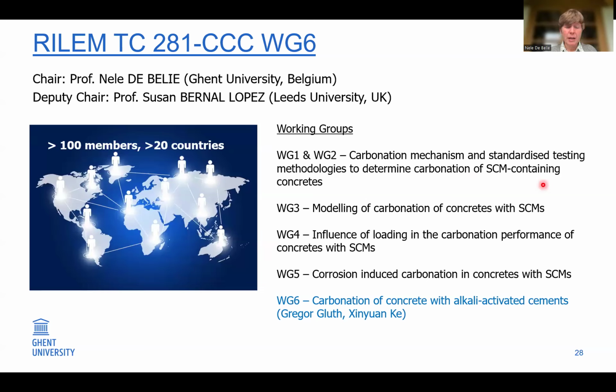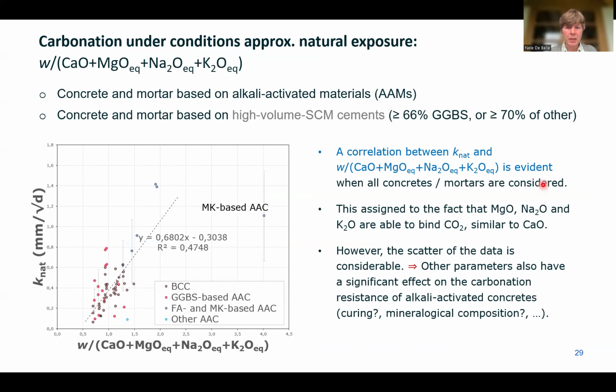Actually, carbonation data were also analyzed in a database specifically for alkali-activated cements by working group 6. And here the analysis indicated that a better indicator of carbonation resistance would be the ratio of water over calcium oxide plus equivalent magnesium oxide, sodium oxide, and potassium oxide amounts, because these are also able to bind CO2 similar to calcium oxide. However, the scatter of the data was quite significant.